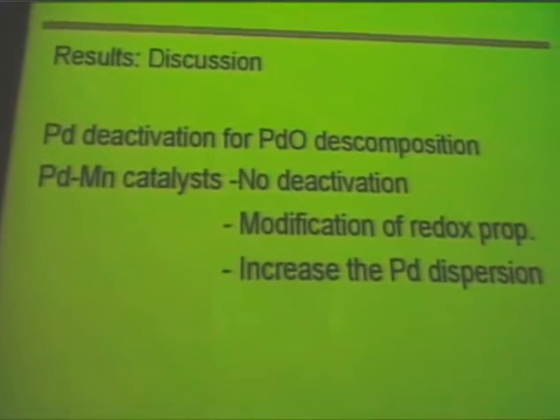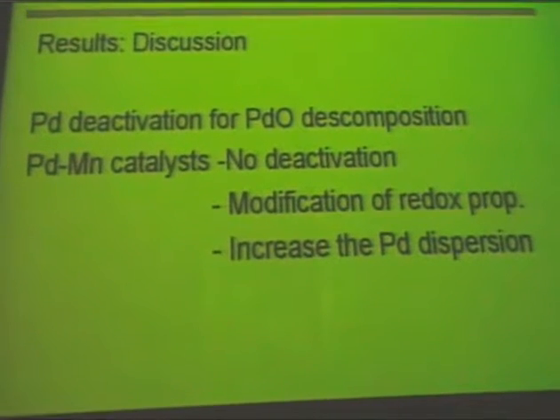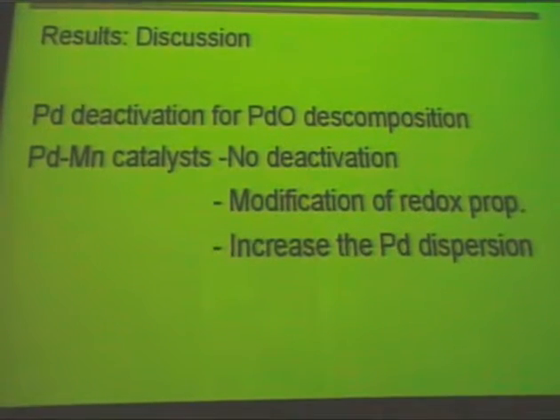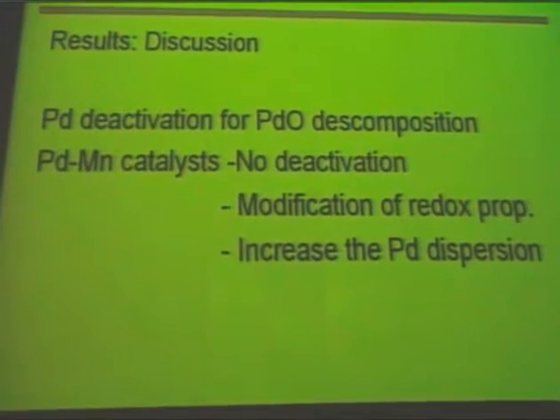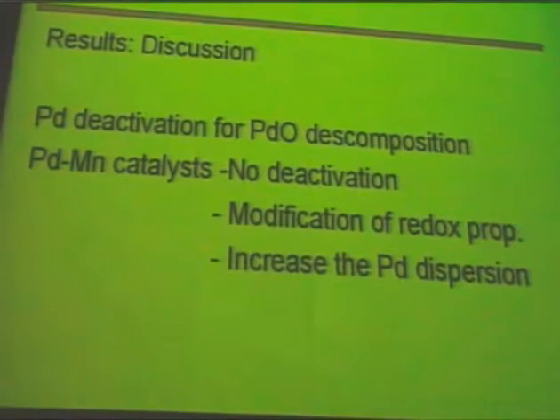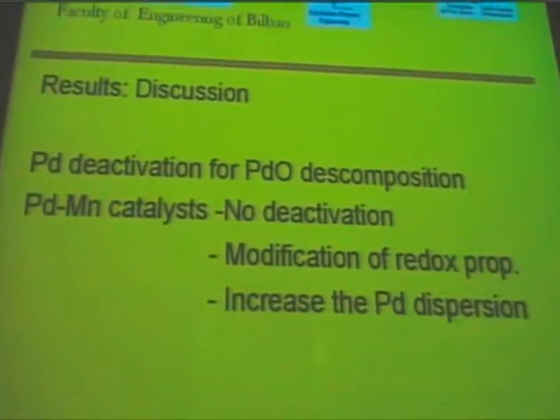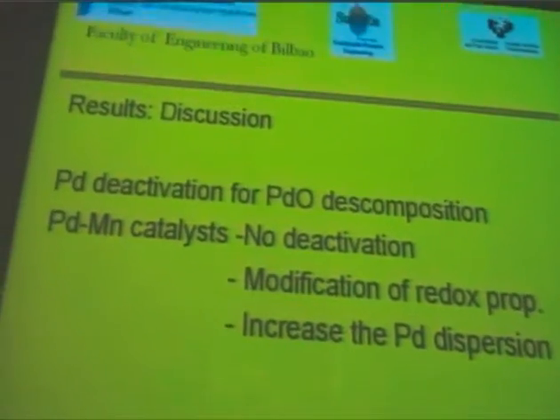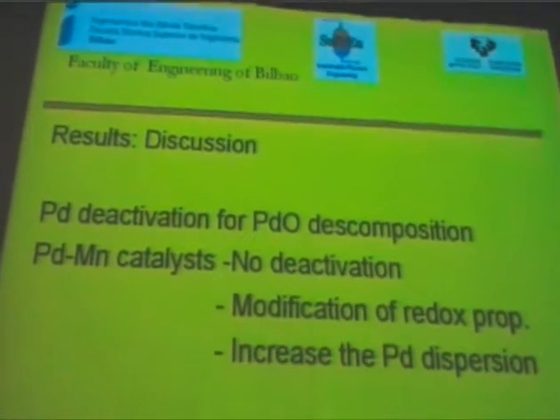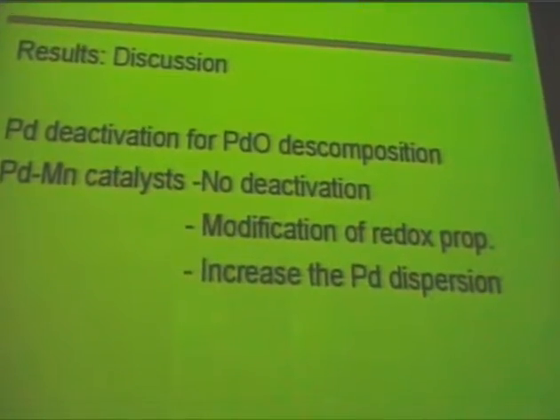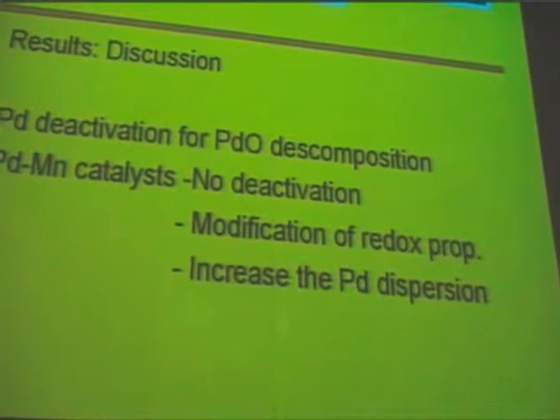At high temperature, the palladium oxide is decomposed to metallic palladium, which is less active for this process, for methane catalytic combustion. Therefore, the palladium deactivation is due to this palladium oxide decomposition. In addition to this, it is probable that other effects of deactivation could occur such as sintering.